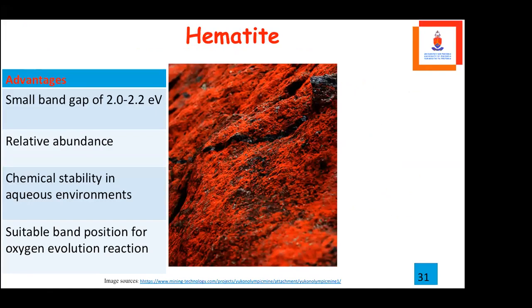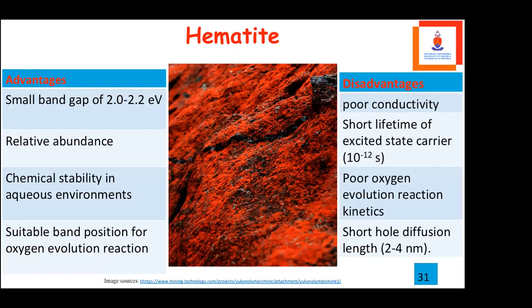When you look at iron oxide, hematite, the advantage is that it has a small band gap, is relatively abundant and therefore cheaper to use, is chemically stable in aqueous environments, and has a suitable position for the oxygen evolution reaction. The disadvantages are that it is a poor conductor of electricity, has a short lifetime of excited charge carriers, poor oxygen evolution reaction kinetics, and a very short diffusion length. With the very short diffusion length, when electron-hole pairs are created, they recombine very quickly.